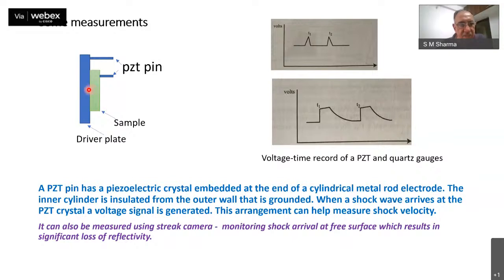And as this shock travels in this, it reaches a second pin. And again, that piezoelectric crystal sends a signal the moment the shock wave makes contact with this. So when the shock wave arrives here, it generates a second pulse. So we know the time difference between these two, and we know how much this distance is. So one can calculate exactly how much the shock velocity is.